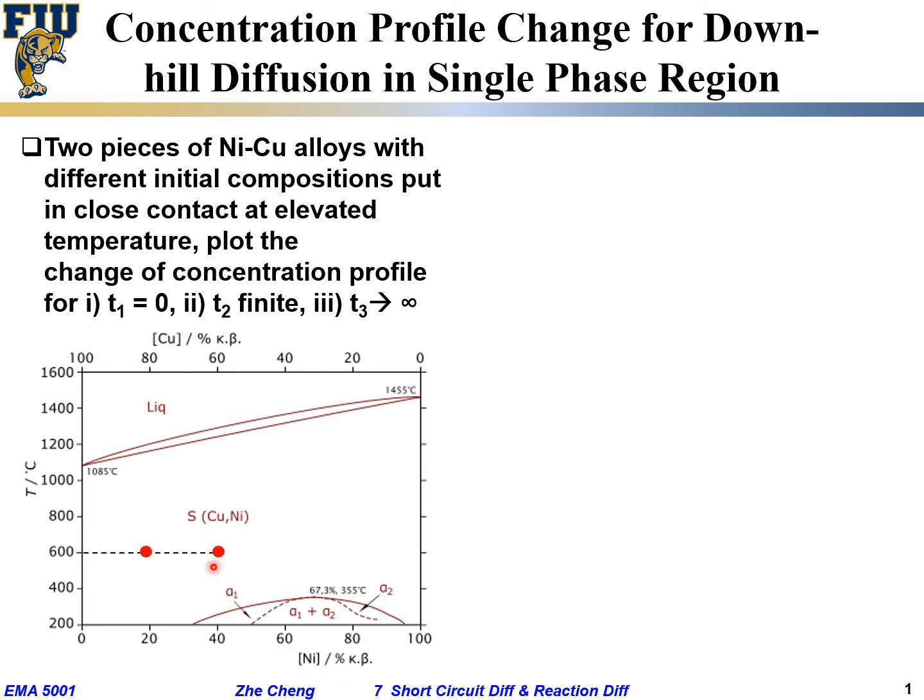Okay, what types of diffusion? Interstitial diffusion or substitutional diffusion by vacancy mechanism? Substitutional, right, by vacancy, because these two elements are very similar, like copper and nickel, similar metal, similar valence, similar atom size, right? So of course they can only go through diffusion by so-called substitutional diffusion, but not by exchange, but by the vacancy mechanism, which is quite often very slow.